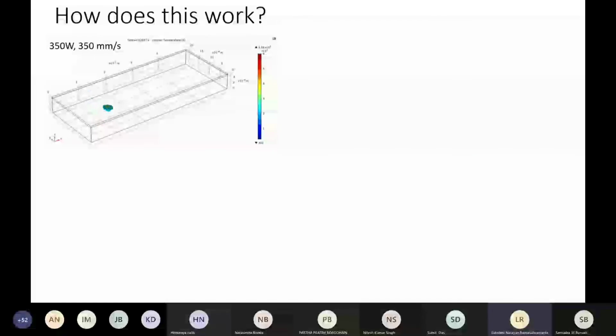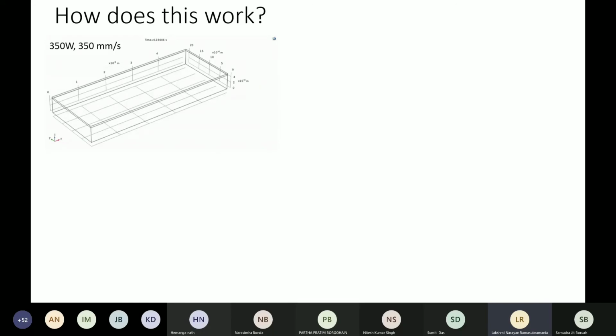So what we did was we tried to simulate the heat in this kind of a strategy. This is nothing but your single stripe strategy where your laser is moving in one direction. Okay, this is how it looks. So it is moving in one direction. You see that small thing is the heat signature of the melt pool. This heat signature will keep moving along with the laser beam wherever the laser moves, because immediately the material will solidify as the surrounding material will cool it. So our heat signature will only move along with the laser beam.